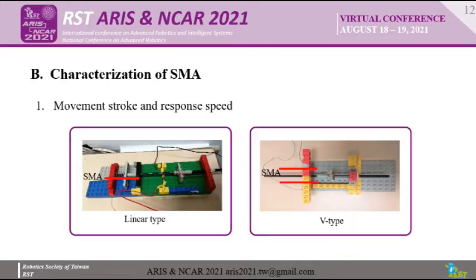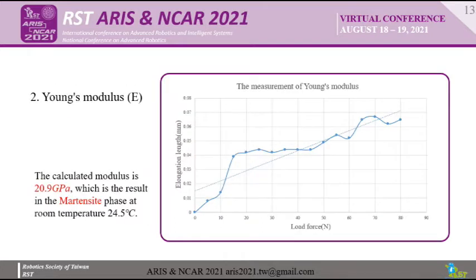First, movement, stroke, and response speed. We installed the SMA with barrel spring in 2 different ways as shown on this page. The linear type and the V-type. It is found that the movement of the V-type will produce a larger stroke. In addition, the cooling time is about 3 times of heating time in the cycle of stroke. Second, Young's modulus. For the relationship between the stress and the strain, the calculated modulus is 20.9 GPa, which is a result in the martensite phase at room temperature 24.5 Celsius.